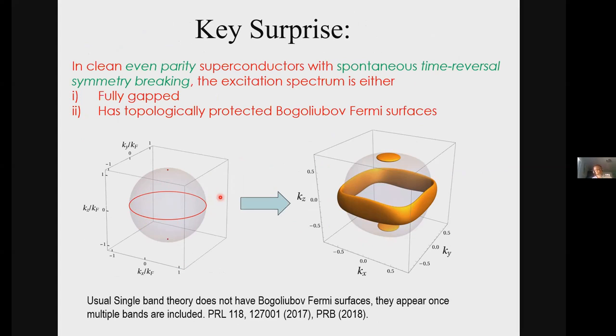What happens is the superconducting state induces by itself a Zeeman-like magnetic field that is momentum dependent. What that does to the nodes that we originally had is that it, what we call, inflates them to form Fermi surfaces. And you'll find these Fermi surfaces are then quite close to the original line nodes and maybe point nodes that we would have expected otherwise.